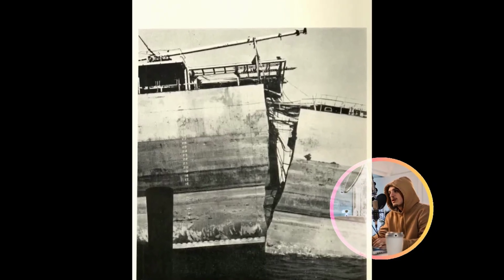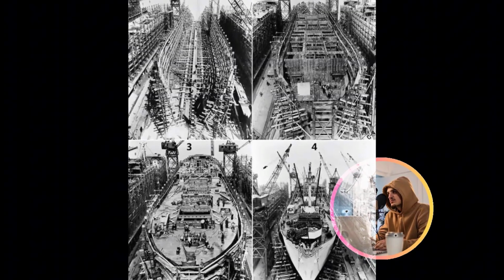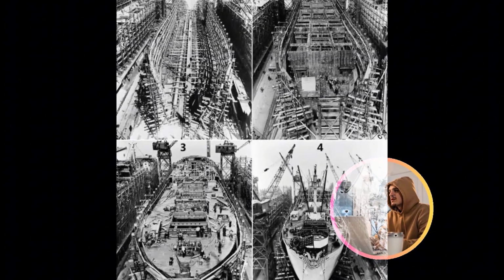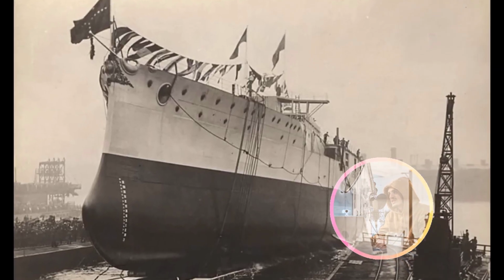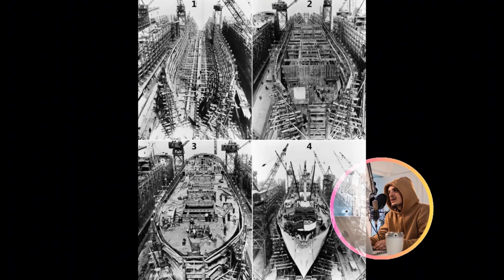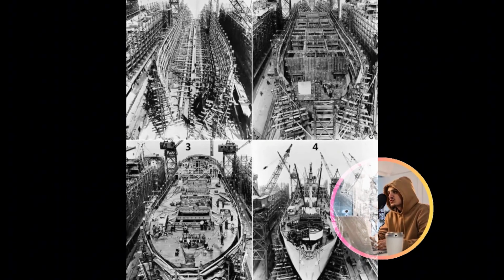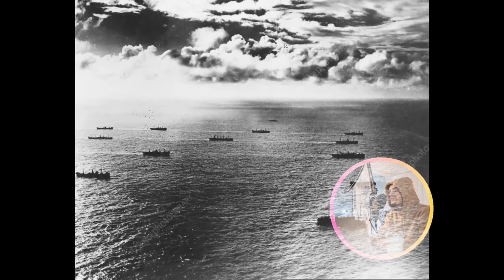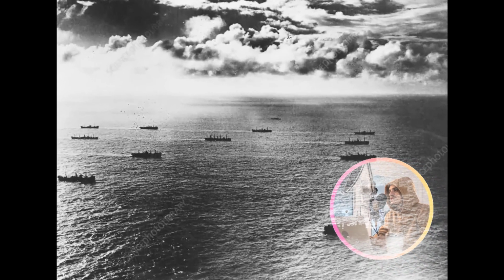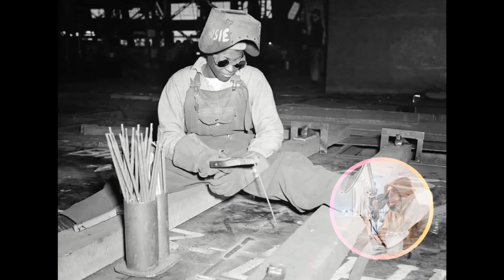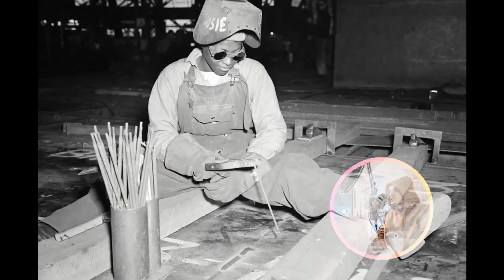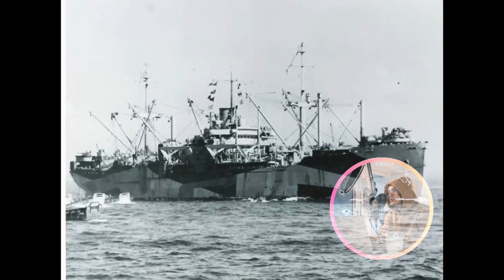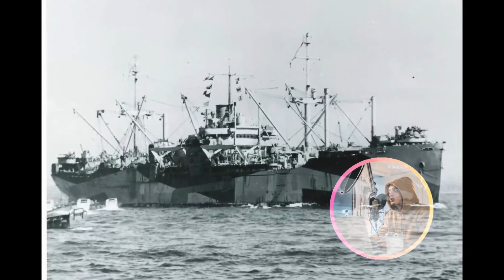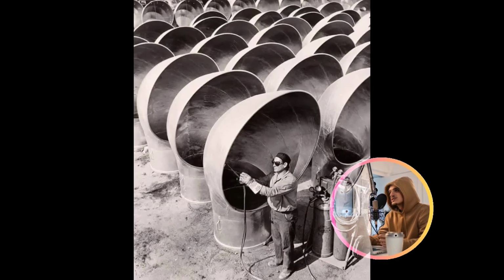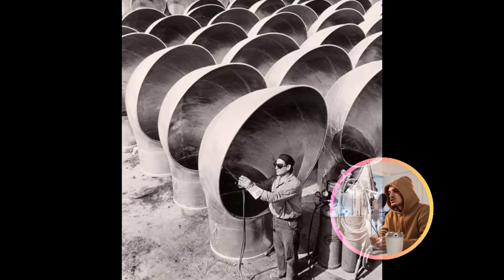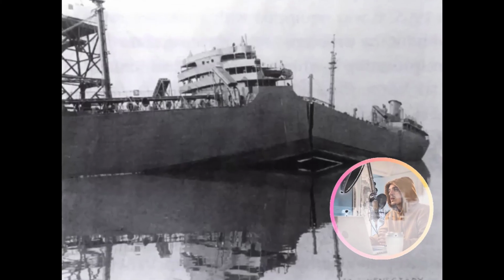Liberty ships were, in essence, succumbing to a phenomenon metallurgists precisely define as brittle fracture propagation. The specific carbon steel employed in their hulls, while designated as shipbuilding grade, performed adequately in warmer waters. However, it underwent a critical and perilous transformation when exposed to the near-freezing temperatures of the North Atlantic. Below approximately 40 degrees Fahrenheit, the steel's inherent ductility, its capacity to deform slightly and absorb stress, collapsed precipitously. Normally, metal accommodates stress by undergoing minor deformation, bending rather than fracturing outright. Cold steel, tragically, loses this crucial flexibility. It becomes dangerously brittle, exhibiting characteristics more akin to fragile glass than the robust, pliant material welders confidently manipulated in California's temperate shipyards.